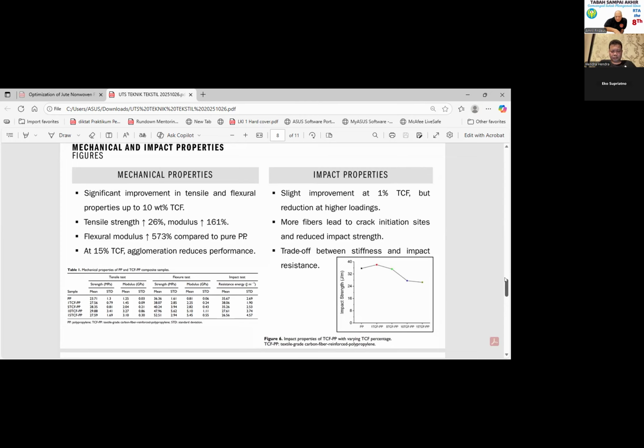So it doesn't mean that increasing the fiber increases the bonding or the strength, because it can create many weak spots. So the sweet spot is clearly around 10% fiber content. This is where the fibers are well dispersed and provide the maximum reinforcement without creating defects.